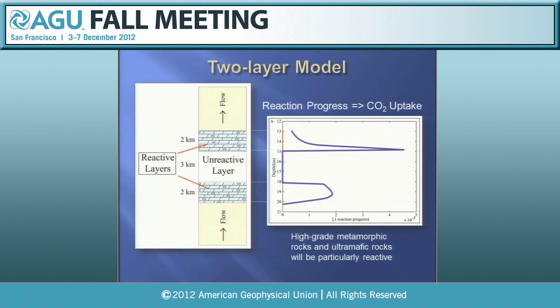What's on the x-axis here is reaction progress, which you can take as proportional to CO2 uptake. So when the fluid that carries some carbonate, dissolved CO2, hits the reactive layer, you get a big jump in reaction progress, CO2 is sequestered. Enter the unreactive layer, nothing happens. Hit the reactive layer, and then we're way out of equilibrium here because the temperature and fluid compositions are very poorly matched, but nonetheless, we have to do what we have to do, and so the fluid goes in and it really reacts and takes out CO2. Bottom line here is that CO2 is being quantitatively removed from the fluid if it hits a reactive rock layer.